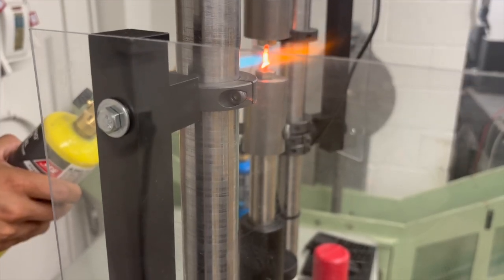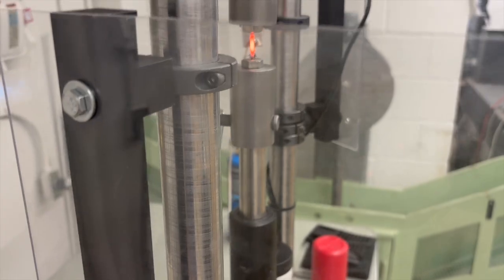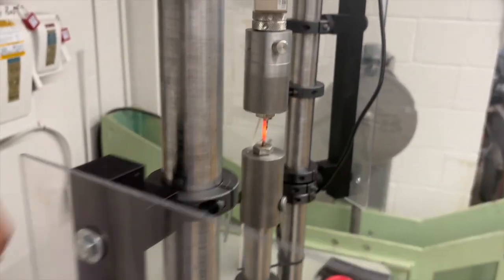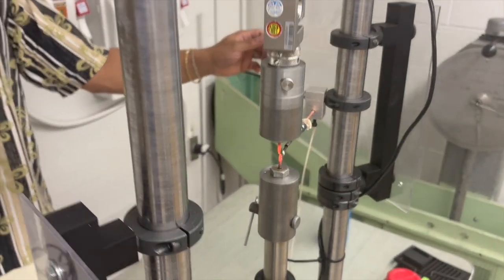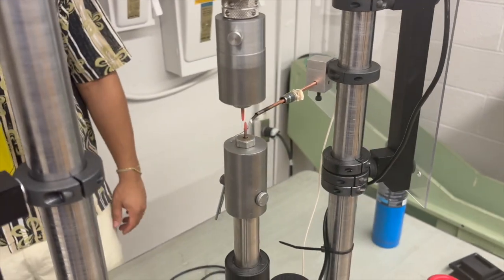2 of them were most important because these were the ones that mimicked hypersonic flight. The first of these is that the heating system shall heat a dog bone sample to 2,000 degrees Fahrenheit in 10 seconds, and the second is that the linear actuator shall be able to apply 1,000 pounds of load.